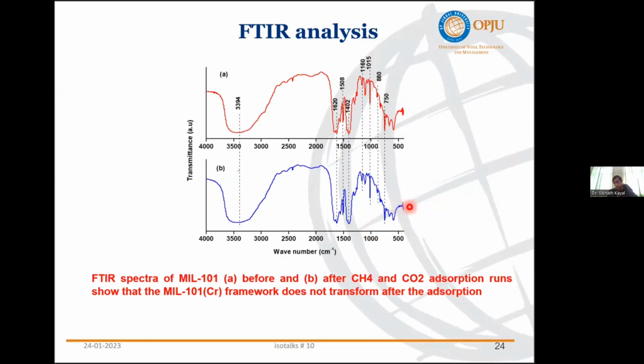Okay, so from this observation we can conclude that the adsorption of methane and CO2 does not deform the MOF structure. That means the MOF structure is completely intact. It doesn't undergo any transformation after methane and CO2 adsorption.